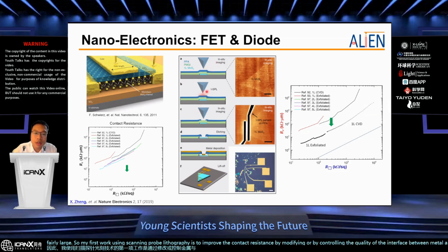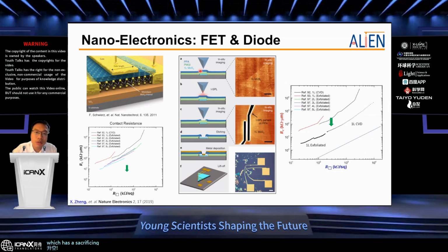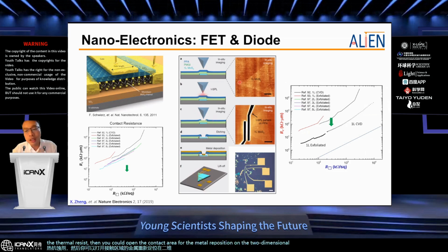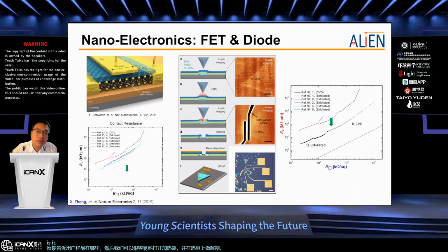So we invented a two-layer lift-off process, which has a sacrificial layer and a thermal resist. The tip is heated and evaporates the thermal resist. Then you can open the contact area for the metal deposition on the two-dimensional materials. So the uniqueness, first of all, is that before patterning, the tip is able to locate the position of the two-dimensional material. This is one of the feedbacks to tell the user where the sample is. Then we could easily turn on the heater and do the patterning on the thermal resist, because it is a sublimation process, so there will be minimal residue from the thermal resist. The really challenging part is the sacrificial layer.